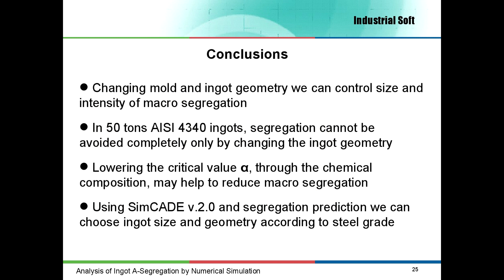As a result of this analysis, we can say that it is possible to control the size and intensity of macro-segregation by changing ingot geometry and its chemical composition. For a 50-ton 4340 steel ingot, the segregation cannot be avoided completely only by changing the ingot geometry. A lower critical value alpha and changing the chemical composition of the steel may help to lower the macro-segregation area size. As the final conclusion, the solidification simulation software and A-segregation prediction technique presented are useful tools that can help to choose ingot size, geometry and the chemical composition of the steel in order to minimize A-segregation and increase the homogeneity of forging products.